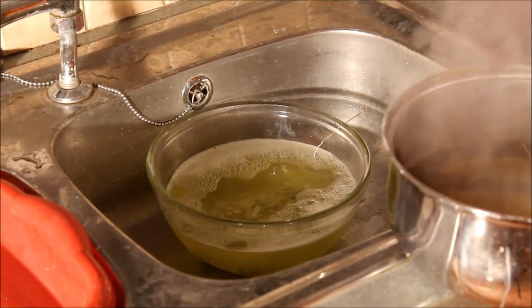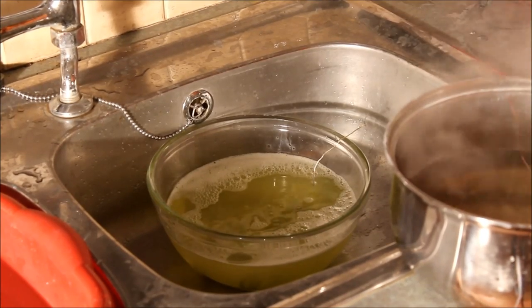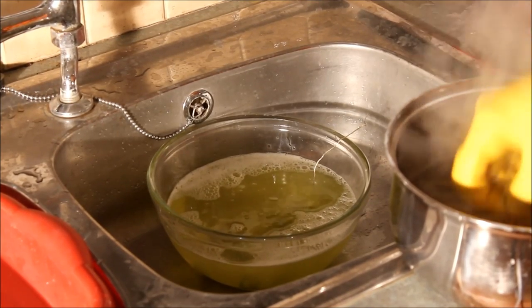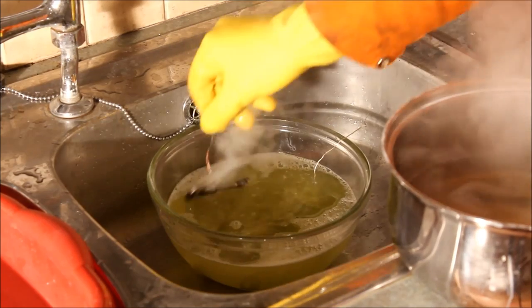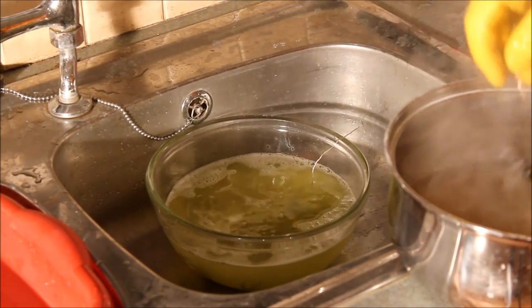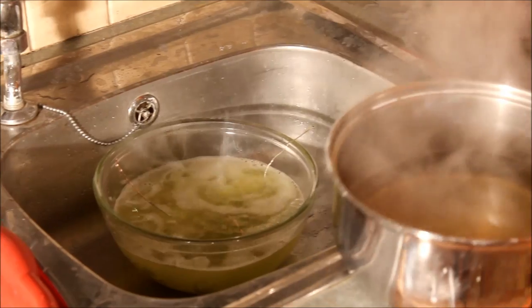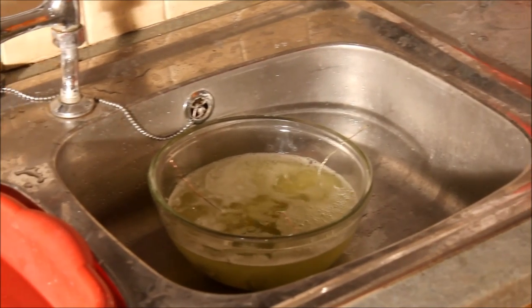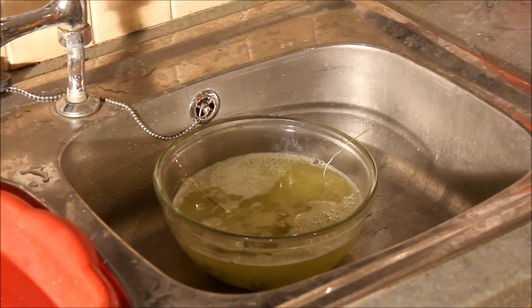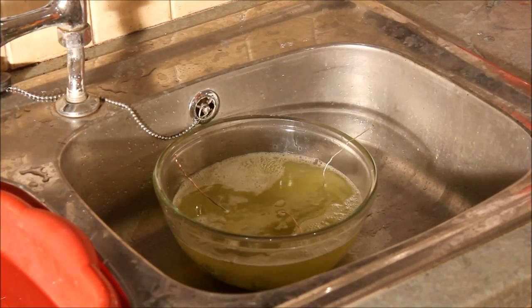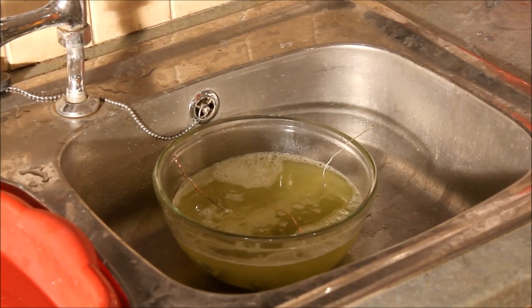Set a timer for between 1 and 4 minutes. 1 minute if they're just quite fresh and just need a little bit of cleaning up. 4 minutes at the most if they're quite rusty still. Now these parts are quite clean, so I'm just going to give them 1 minute in the bath there, and that should just etch them enough that they'll take the zinc plate.